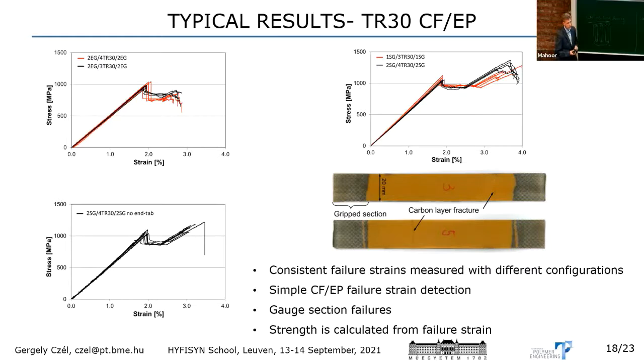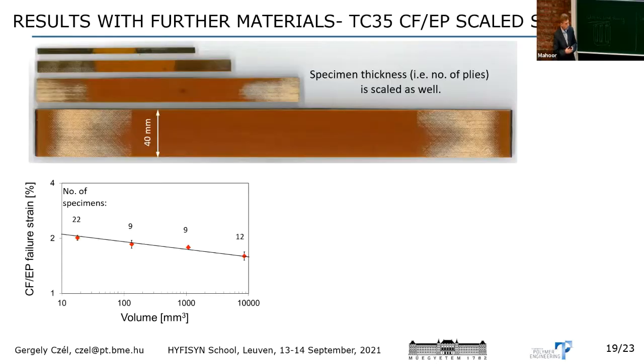But as a downside of this technique, we cannot calculate the strength of the specimens immediately. We need to back calculate it from the failure strain, which can be measured accurately, preferably with a video extensometer or maybe a bonded electronic strain gauge. But for the strengths, we need to rely on a reasonable modulus of the specimen, which can be measured separately on monolithic specimens. And again, this is a problem because we need to test the normal specimens as well. Or we are simply happy with the failure strains. And actually, in many cases for design, the engineers set a strain criteria. Hopefully I'm right. And so we may find that it's enough to determine the failure strain of the material.